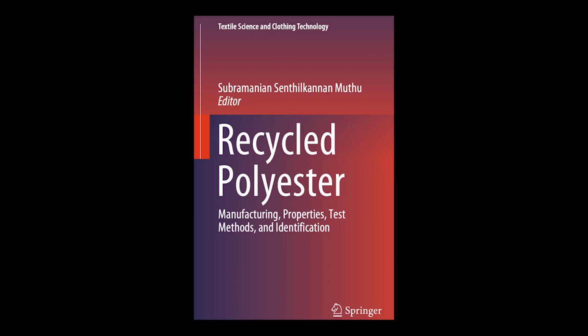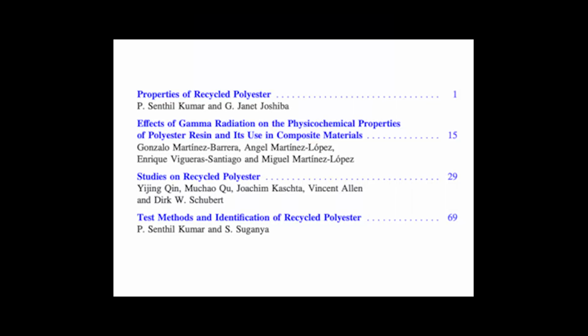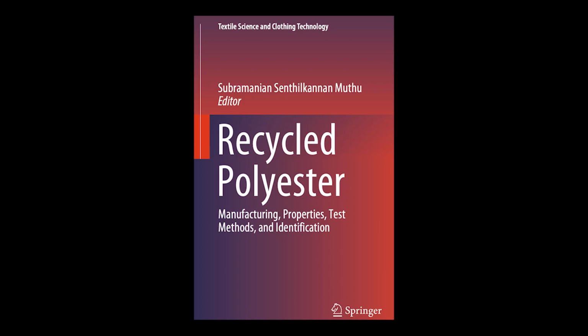Okay, let's step back from the technical details for a second. If you had to give the single most important takeaway from this melt spinning study, the bottom line, what would it be? The real breakthrough demonstrated here is this. The study proved it's entirely possible to produce PET fibers from bottle-grade recycled copolymer PET, the clear rPETB, that possess properties like desirable tenacity, strength, outstanding elongation at break, stretch, and excellent fineness, thinness, that are similar to fibers produced from the standard fiber-grade virgin homopolymer PET, vPET1. That is huge. It's basically saying high-performance substitution is technically possible right now using existing waste streams if they're clean enough. That's the implication, yes.